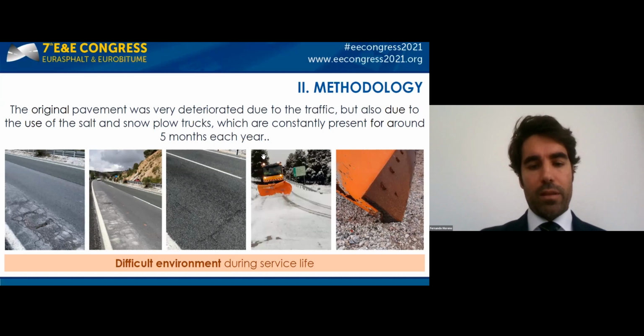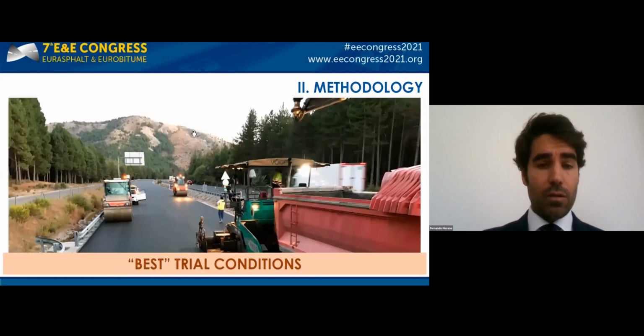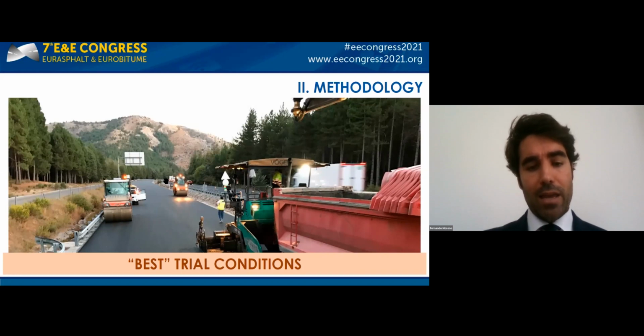It will also withstand a difficult environment during the service life, because the original pavement was very deteriorated due to the traffic, but also because during its service life it will be in constant presence, for around 5 months each year, of salts and other fondants and the passage of snowplow trucks. So we can say that this material was tried in the best trial condition, because it was the most demanding.